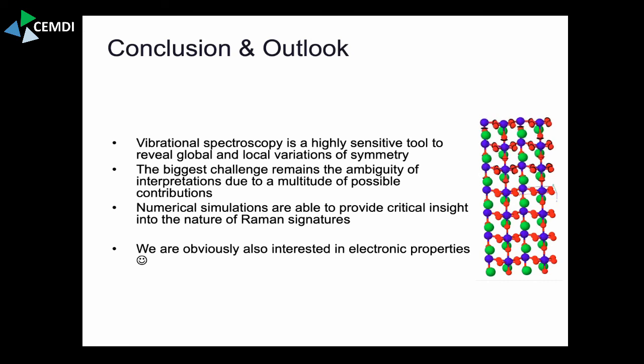it is not a symmetry again, because every phonon will see something differently aperiodic. So you average over different aperiodic structures. But what's important is that you have each and every time this broken inversion symmetry. The phonon propagation is in the ballpark of 4 nanometers. In magnesium oxide, if you calculate the volume, there are several isotopes within the propagation length of the phonon. And that means that the least thing I would expect, and that's been observed by the way in silicon, is the peak broadens. You get peak broadening, you get small peak shifts because you're averaging over these different bonds.